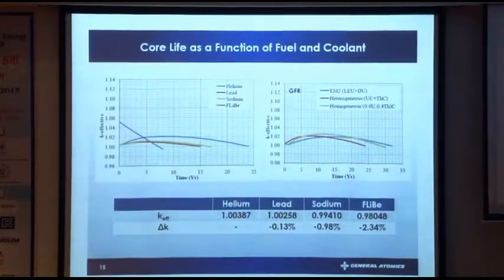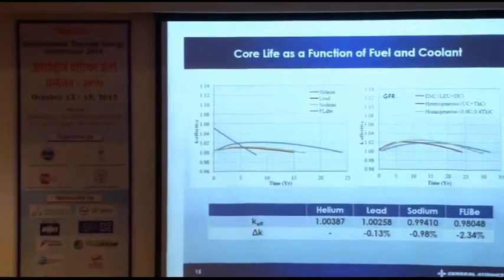And this chart here shows the core life. Again, this one compares the helium, lead, sodium, and fluoride coolants, and again, keeping everything else the same, how the length of the fuel cycle we can achieve here. So helium is the longest core, which is about 23 years, and this is the heterogeneous case. The lead case is about 14 years, followed by sodium 16 years, and the molten salt, it's not critical after about 8 years.